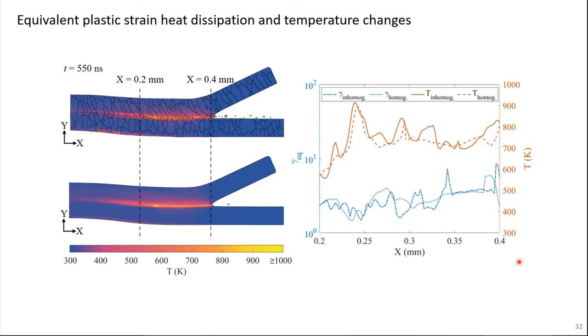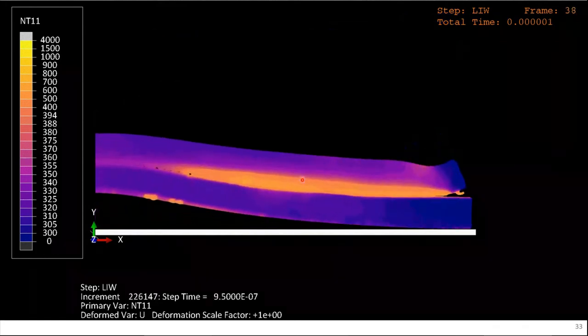So if you look at the inhomogeneous versus the homogeneous for the equivalent plastic strain, that's the blue curve, you notice for the inhomogeneous, you get numerous peaks compared to the relatively smoother homogeneous model. Likewise, for temperature with the inhomogeneous, which is a solid line, you get these numerous peaks occurring, whereas for the homogeneous, which is the diagram at the bottom, you get relatively fewer spikes. So there's definitely an influence of microstructure on the response that we're getting in terms of heat dissipation, the temperature profile, the jetting phenomena.